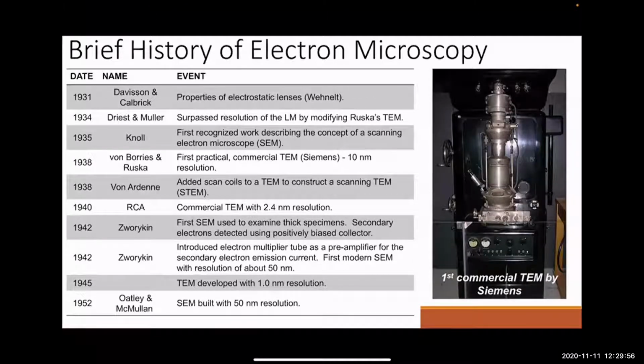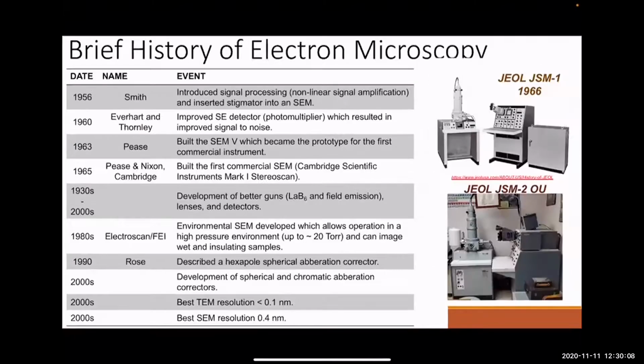So historically, TEM, transmission electron microscopy, came first. SEM as a concept was right around that time, but you don't see a commercial SEM until much later, 1965. And so you can see some early SEMs here. And so in some sense, SEM got a much later start in life. And as I mentioned, the concept was there, but the problem was they didn't have a good enough detector to detect these scattered electrons coming off your sample.